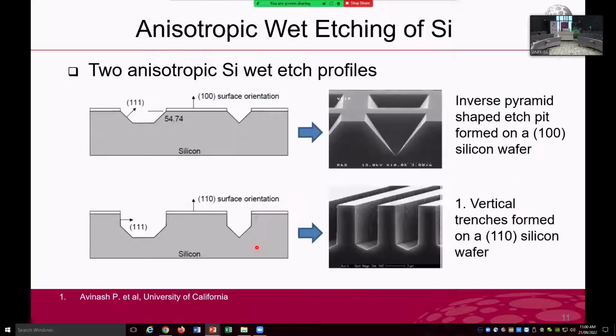And the next slide shows these anisotropic etch profiles formed on a 100 surface orientation wafer. This is an inverse pyramid shaped etch pit structure. And the other one is formed on a 110 surface orientation silicon wafer. We can see these vertical trenches formed by using the wet etching technique. In both cases, I would like to get your attention that the side walls are formed by 111 planes. That's because the etch rate of 111 planes is extremely low in KOH solution, and that plane acts as an etch stop plane.